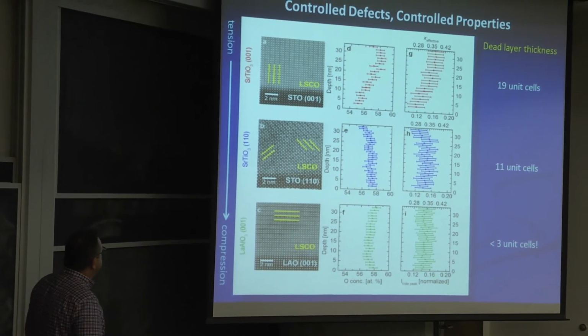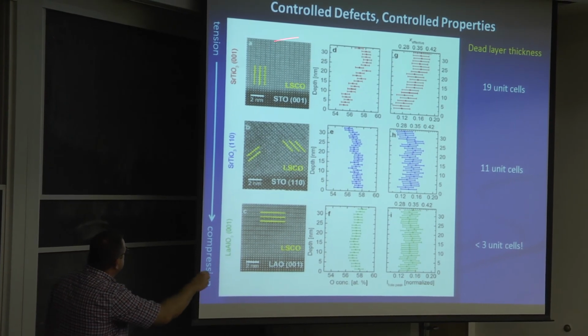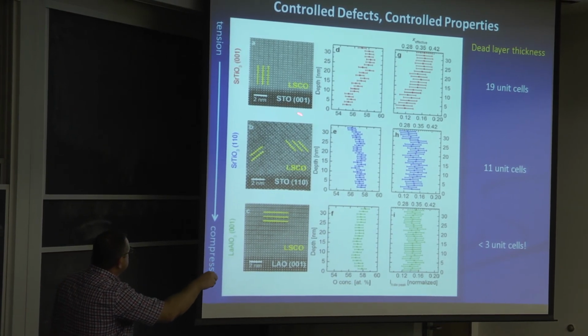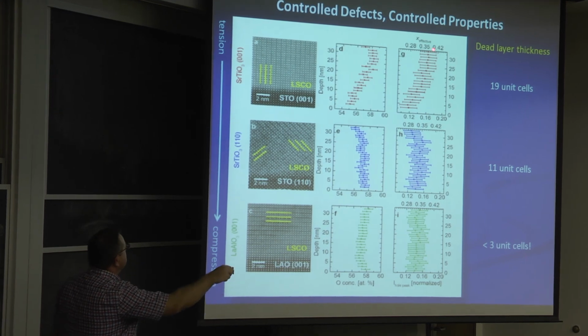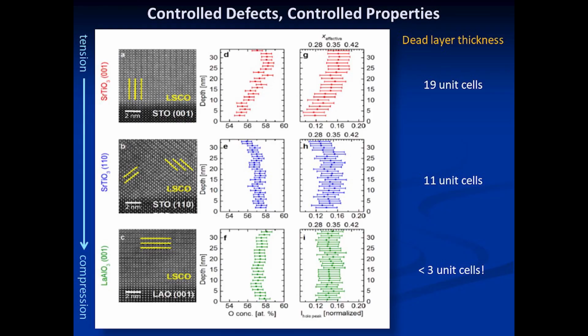So this is really technical, but I just want to show you what happened when we did this. This is what I showed you already, the STO-001 with these perpendicular stripes. This is the oxygen crashing down. This is the holes crashing down. You go to these other substrates. This is what everybody had been using, and the oxygen content as a function of position just becomes absolutely ramrod flat. It also gets smaller and smaller as you go to these compressive strains. This is what happens to the dead layer thickness. 19 unit cells, 11 unit cells.